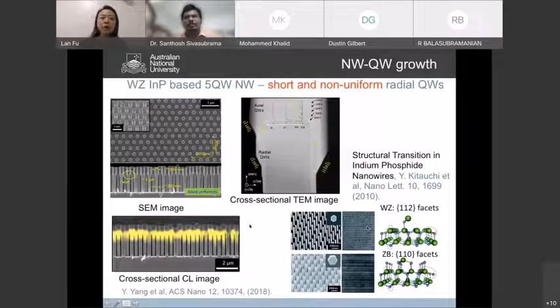And of course, you can see that we can incorporate more quantum wells, because more quantum wells means more gain and also better emission efficiency, more powerful light emission. But the problem we can see by incorporating multiple quantum wells is that the morphology becomes less uniform. We have a very short quantum well region forming in those nanowires, which is limiting the application. So what we want to do is figure out how we can create more uniform quantum wells in our nanowire structure.